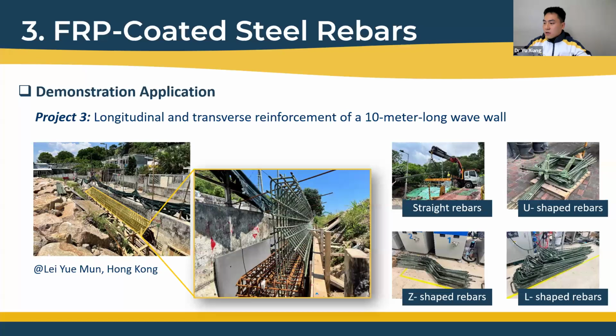If on-site rebars need this FRP coating, we can also do this on-site. For the third question, other than applying FRP coating to the hoop and special treatment of both ends, we currently use a plastic cap on the end of the FRP-coated steel rebar before applying the coating layer. After treatment of the steel rebar—descaling, oil removal—we apply the cap, then do the filament winding to make the FRP coating layer. So the two ends will be properly protected by the caps.